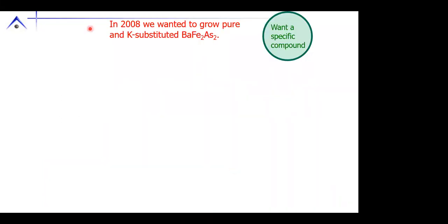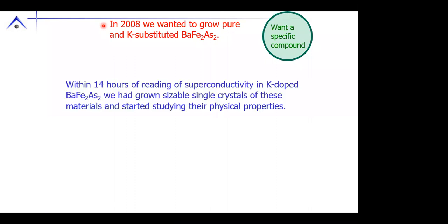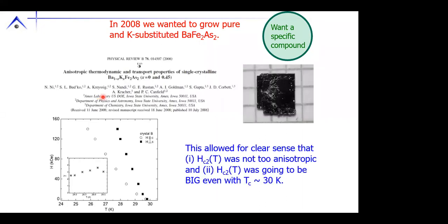So a final example of one specific compound, and then we will go to the more interesting motivations, okay? In 2008, we wanted to grow pure or potassium-substituted BaFe2As2, okay? Within 14 hours of a posting that polycrystals of BaFe2As2 doped with potassium could superconduct, we were able to have single crystals. We were able to grow crystals that then allow us to look at the anisotropic properties.